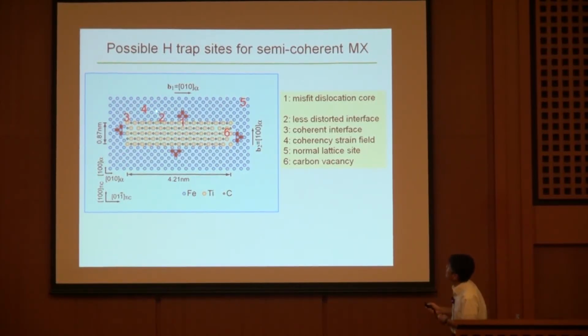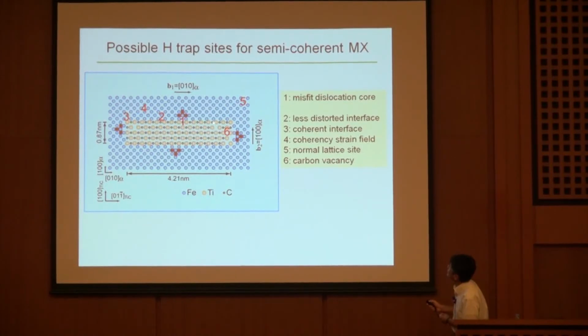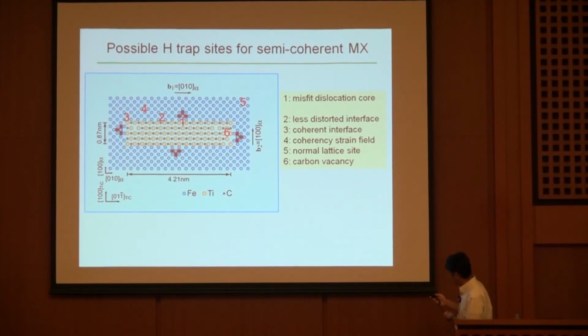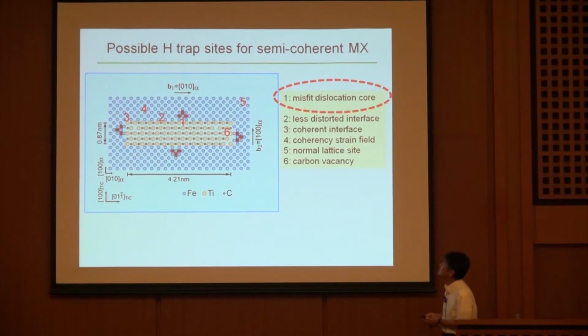Somewhere, normal lattice site here, but the possible trapping site, I would like to say the misfit dislocation core is the key for this particular case. Why?